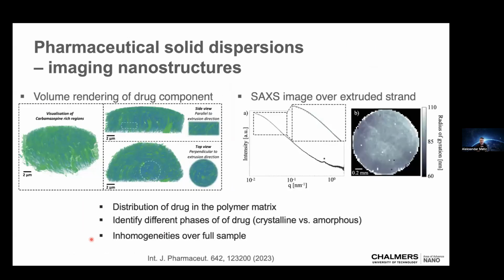In a previous experiment, which was not done at ForMAX, but was done at cSAXS in Switzerland, we could first, with imaging, reveal, so the right image here shows different polymorphs of the drug distributed in the polymer matrix, which is a cellulose-based matrix, by the way. And where you can see that there is kind of a swirling pattern, kind of alignment of these domains. And this has to do with extrusion. So you're basically seeing the extrusion direction. So this was done with a particular nanotomography method. And then we wanted to understand, so is this really representative, what we extracted? Because it was a very small sample.